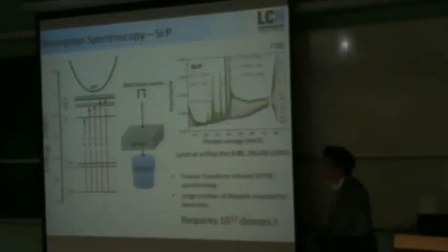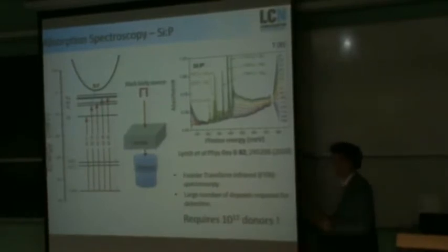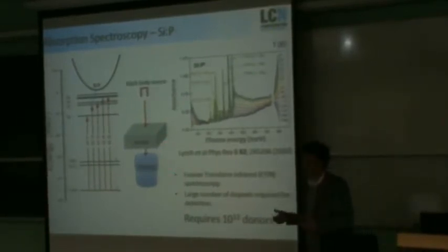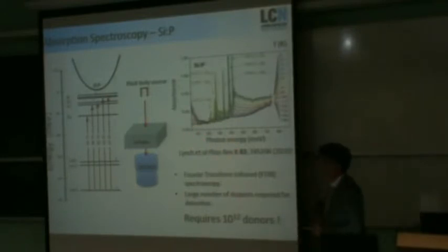So measuring these excited states in an ensemble or in a bulk sample is actually quite easy to do. There's quite a few studies over many decades that have looked at these excited state spectra. And here's a good example where they looked at the temperature dependence of the excited states. You see at elevated temperatures, you start to see transitions from higher 1s states to further excited states.